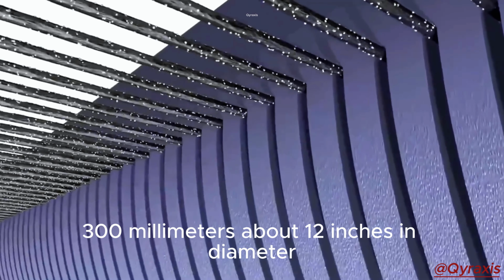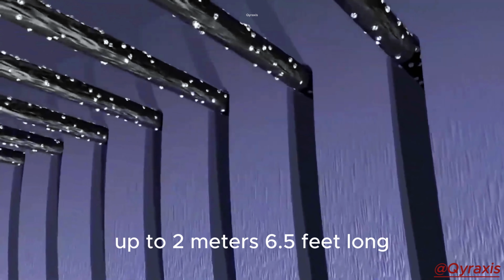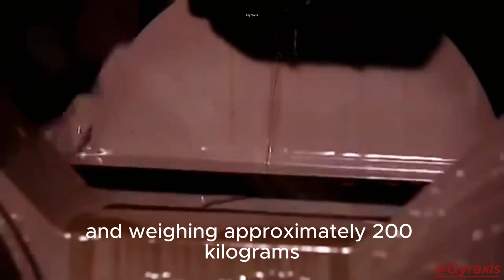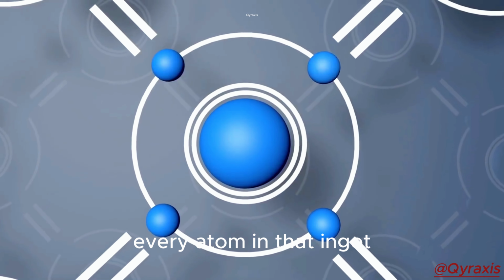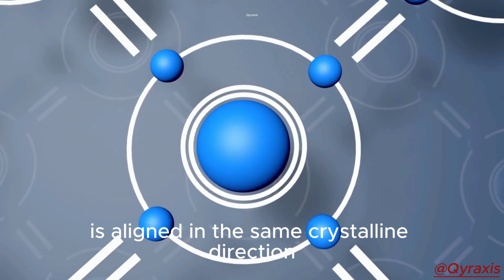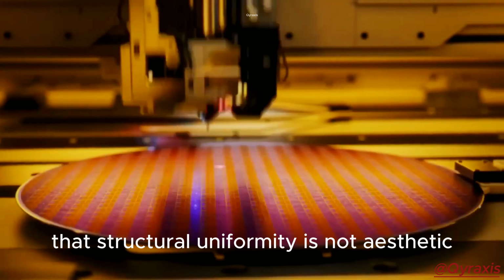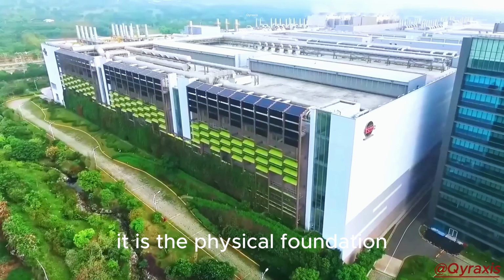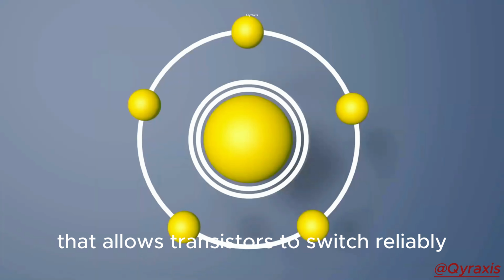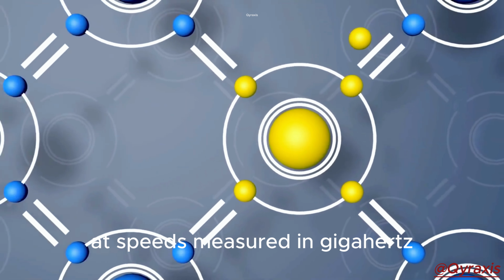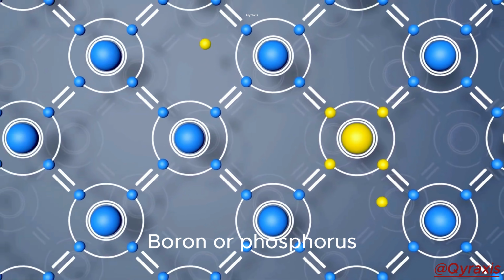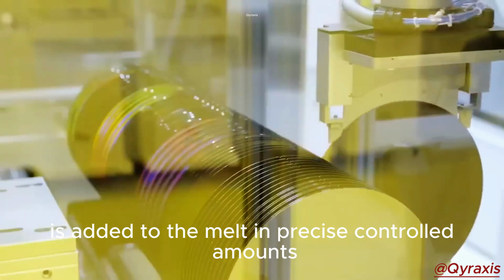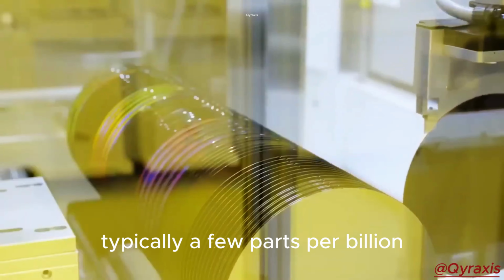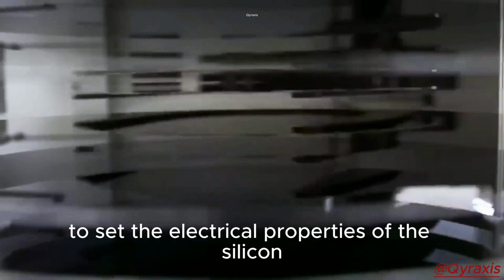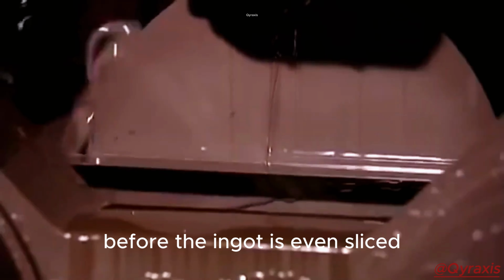The result, after roughly 24 to 48 hours of continuous pulling, is a cylindrical single crystal ingot, 300 millimeters, about 12 inches in diameter, up to 2 meters, 6.5 feet long, and weighing approximately 200 kilograms, 440 pounds. Every atom in that ingot is aligned in the same crystalline direction. That structural uniformity is not aesthetic. It is the physical foundation that allows transistors to switch reliably at speeds measured in gigahertz. Boron or phosphorus is added to the melt in precise, controlled amounts, typically a few parts per billion, to set the electrical properties of the silicon before the ingot is even sliced.